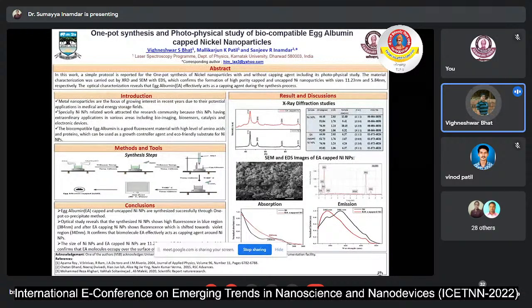Then black colored slurries of the sample with evolution of hydrogen gas will occur. This process is an instantaneous exothermic reaction. Then I kept it for 10 hours at room temperature. After 10 hours, using an external magnet, I removed the black colored slurries and repeatedly washed them with double distilled water several times to remove the unwanted impurities present in the sample. The obtained slurries will be dried using an oven and collected in an